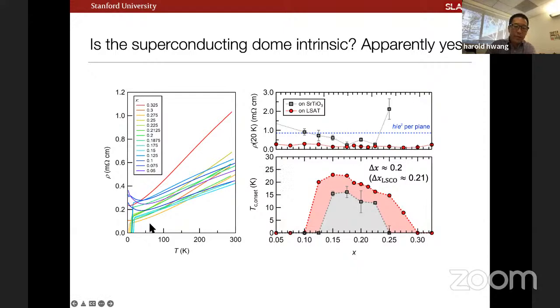So I'll go into some of the details. I'm sure this is too busy to look at, but again, the scale of the resistivity of the whole problem has moved down. And in terms of superconductivity, first statement is that there's still a dome, but it's grown a little bit, right? Both in terms of Tc and the width of the dome. It's actually quite surprising, or maybe at this point a coincidence, we're not sure, but now the breadth of this dome is almost identical to that in the 214 cuprate problem.